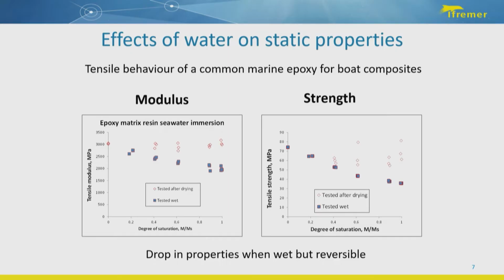So what if we have water in the material? Well, one of the things we see in the traditional materials is that the modulus drops. In this case, for this marine epoxy, we've lost about 30% of our modulus when we've reached saturation, which in this case would have taken probably a few months. And the strength has dropped by about 50%.